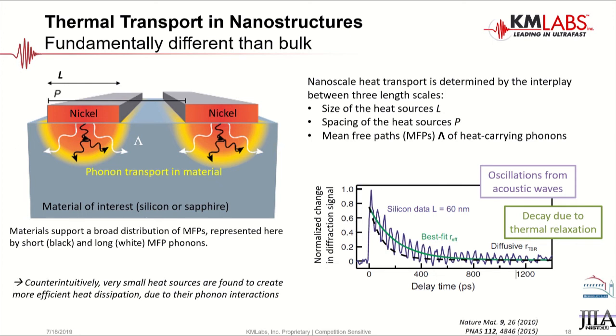But the researchers actually found that there's a threshold where once these things get small enough and close enough together, the phonons start to interact with one another from the different heat sources and actually contribute to the efficiency of that heat transfer process. So that's a pretty interesting finding if we want to keep designing smaller and smaller heat-producing structures.